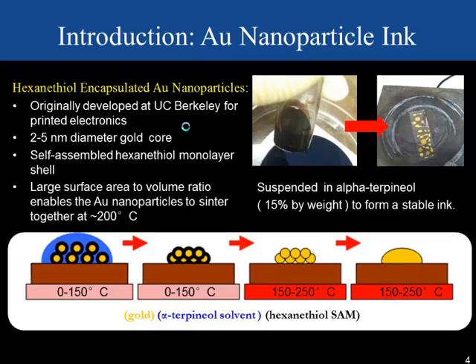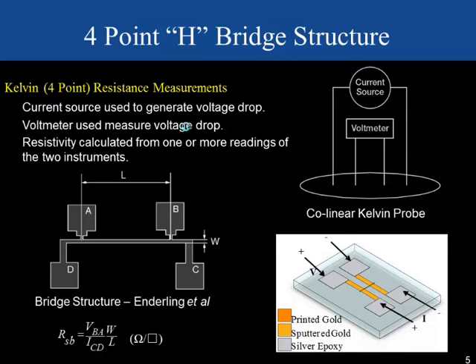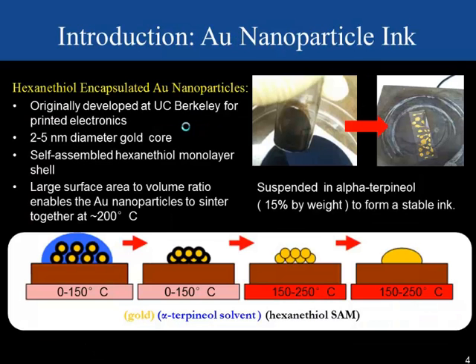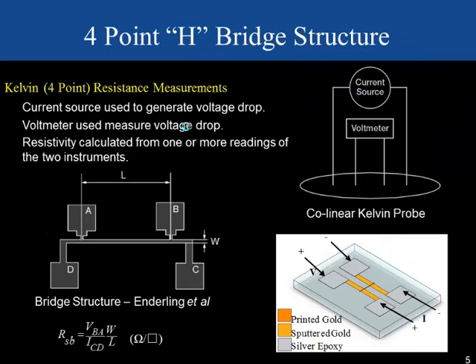As you can see here, first we deposit the ink on a heated substrate to rapidly evaporate away the carrier solvent. At which point we can ramp the temperature of the substrate, at which point the organics begin to break down and sublime away, and then the nanoparticles will begin to sinter together and ideally form a coherent gold structure. Understanding this process and the resulting films is the subject of study here. There are two ways to actually monitor this process. One is visually. The ink goes from a black organic to a gold color, or alchemy as my mother refers to it. Alternatively, you can monitor this process by watching the resistivity of the films during sintering.